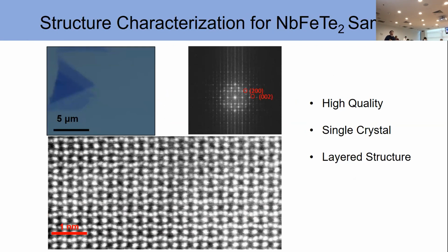And here is the structural characterization of our NFT sample. On the left is the optical image of the exfoliated NFT thin flakes. As you can see, the triangular boundary of our exfoliated samples shows that our crystal is of high quality. Also, this electron diffraction pattern shows a good single crystal signature. And last, our TEM image clearly shows the layer structure of NFT.